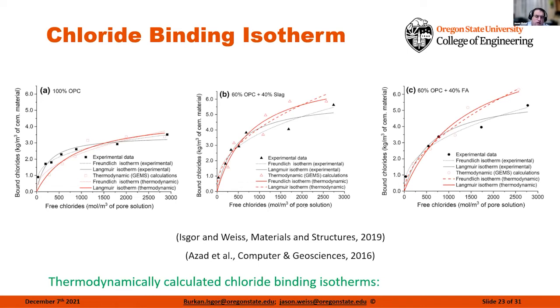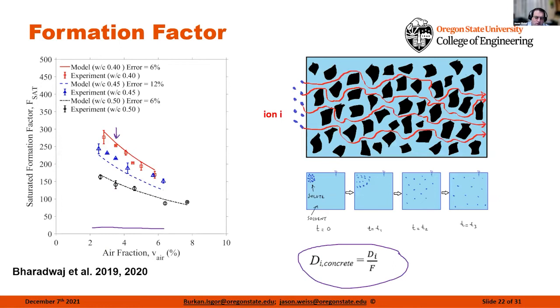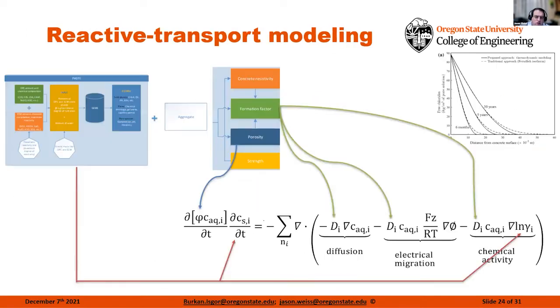So what I would take away here is if we can predict the diffusion coefficient and we can predict the binding coefficient, all of a sudden we can now start to predict some of these complicated chloride ingress profiles. And we're doing this all before we've ever had to even make a concrete. So one of the huge advantages of this type of approach is we can do this for millions and millions of concretes and predict these reactive transport models and start to now predict things like how long will my concrete last in corrosion? How long will my concrete last when it's exposed to de-icing salts?